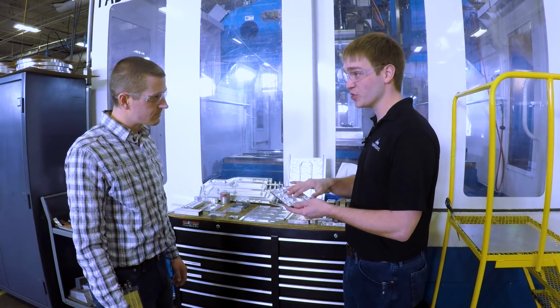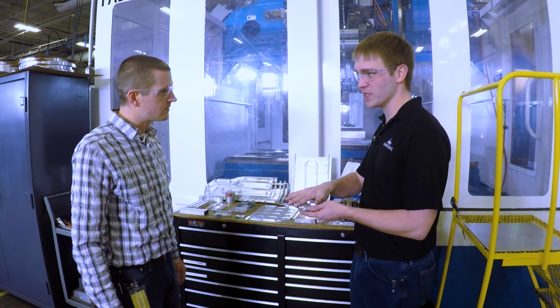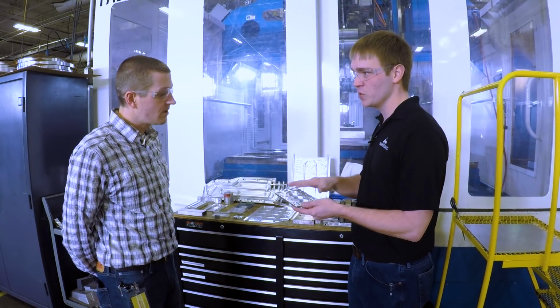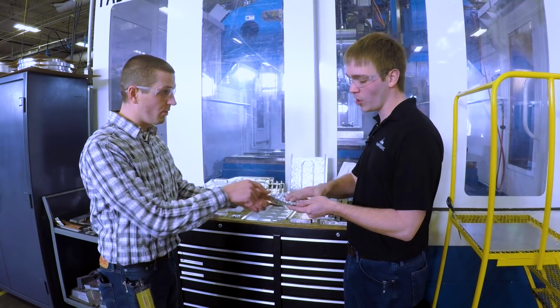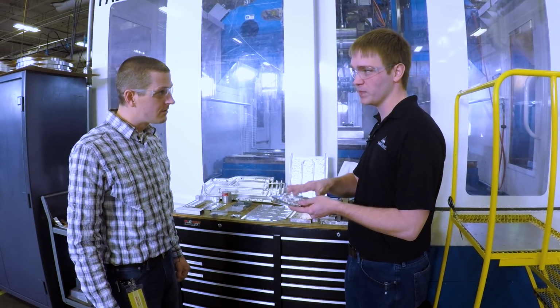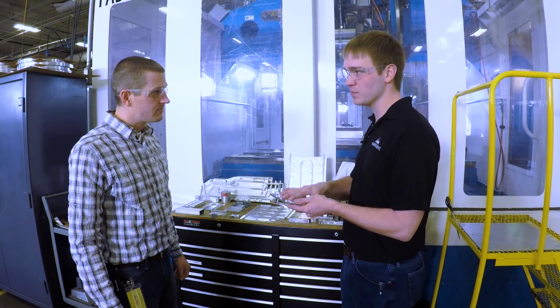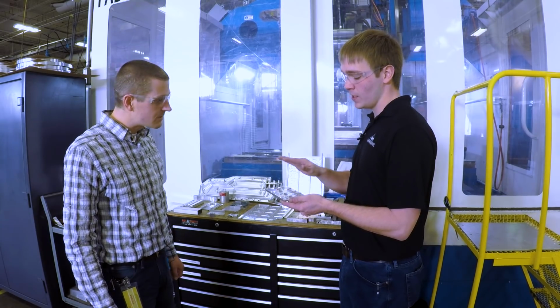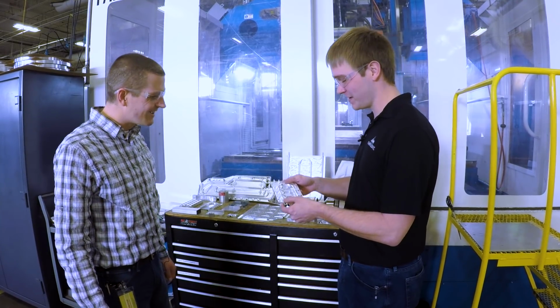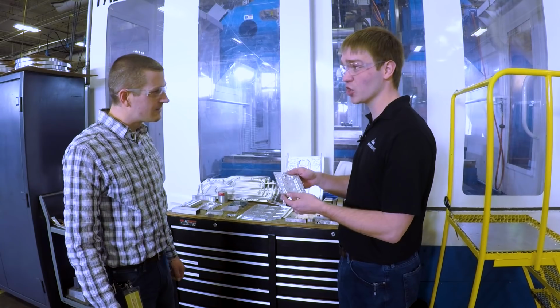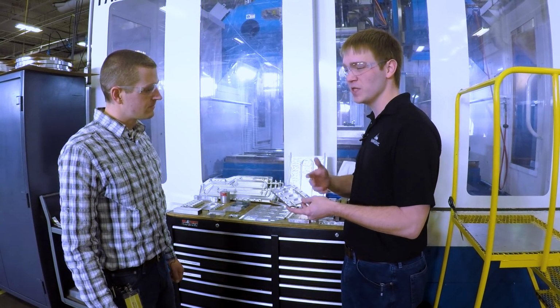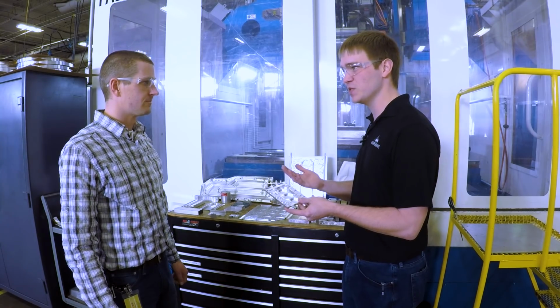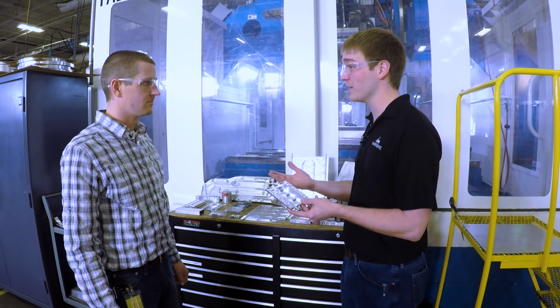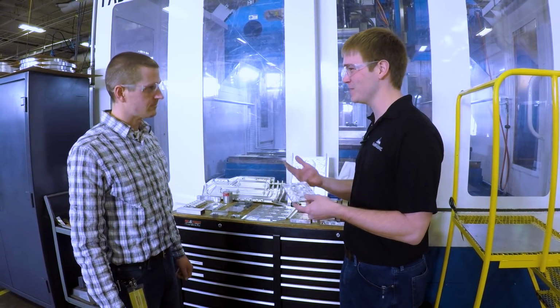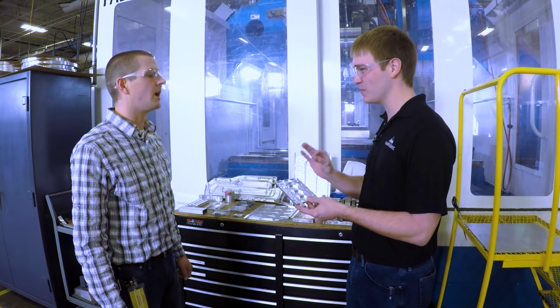It's got a burst pressure above a certain threshold. In our circumstance, it's about 3,000 PSI. That means this 35 thou aluminum wall can maintain over 3,000 PSI burst pressure. Exactly. That's amazing. And it also has hermeticity, which, when you're considering the process is nothing but continuous welds, there's a lot of opportunity for there to be discontinuities that would be a leak path. And when you're putting something into space and you have no ability to fix the leak, it has to be perfectly sealed.